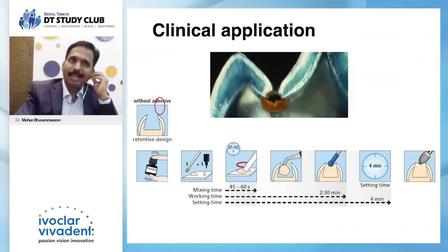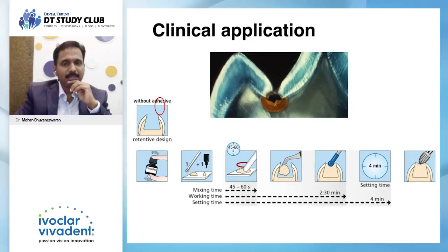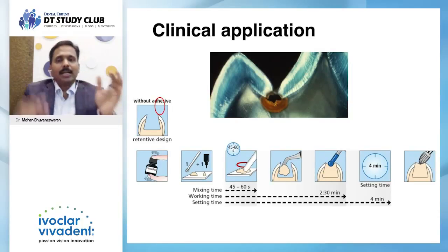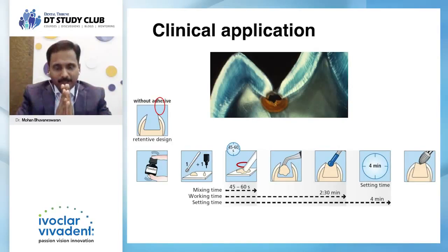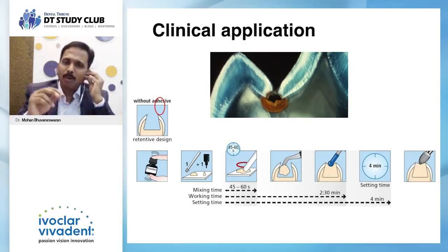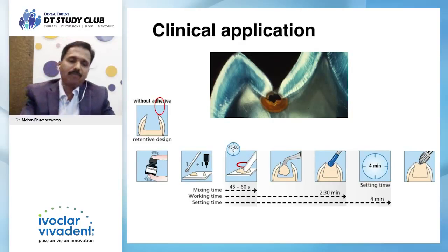So in short, the clinical application would be the cavity preparation. Look at that, a retentive cavity preparation, and then you dispense it, mix it, place it, finish it, and send the patient back home. The setting time is 4 minutes from the start of mixing. The most important point I would love to suggest is the mixing. Mixing is very, very important, right? It determines so many factors. So I would love to play a short video on mixing.